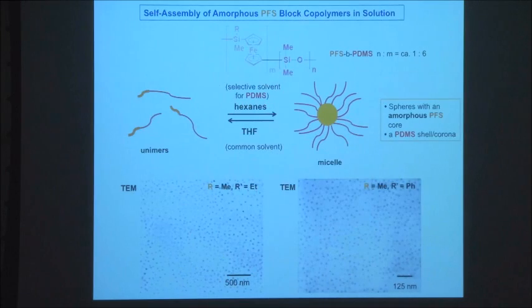Okay, so moving to self-assembly. So first what I wanted to show is what happens when you take a PFS block copolymer where we have an amorphous PFS block. So this is one with methyl ethyl or methyl phenyl PFS block and a polysiloxane co-block. Block ratio here is about 1:6. And if you put this into THF, THF is a good solvent for both blocks. So you get what are called unimers. So these are individually dispersed block copolymer macromolecules, because you're in a solvent that's good for both blocks.